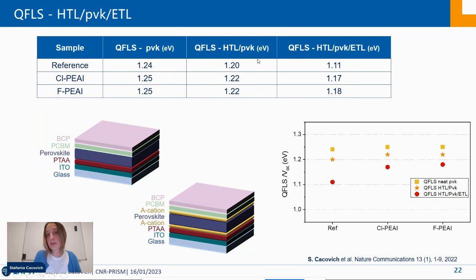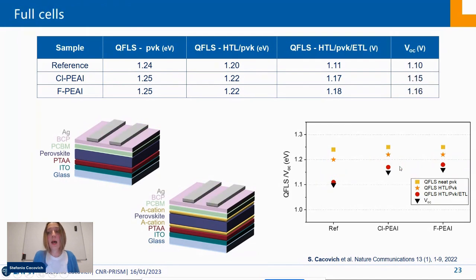If we compare these two columns, the variation between the reference and the passivated samples is not so high. But if we go to the second interface, here we can notice that we have a real improvement, because the non-radiative losses are reduced by several tens of millielectron volts. And then if we compare these values with the VOC of the devices, we can see that there is a good agreement between the optical and electrical characterization.